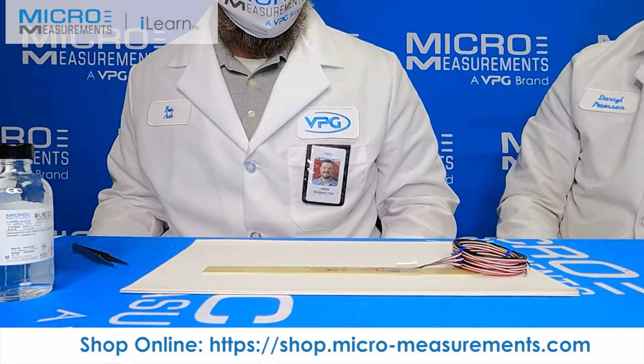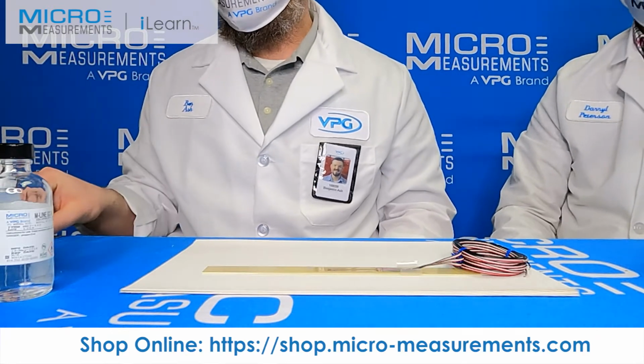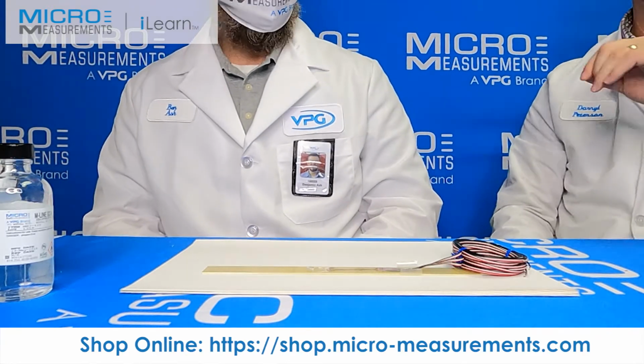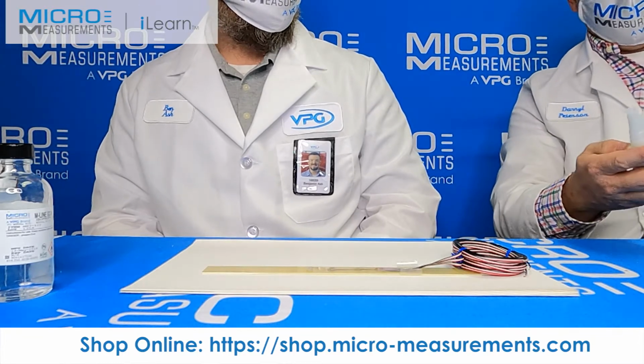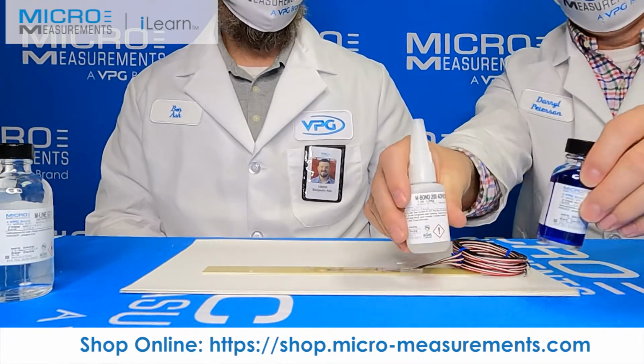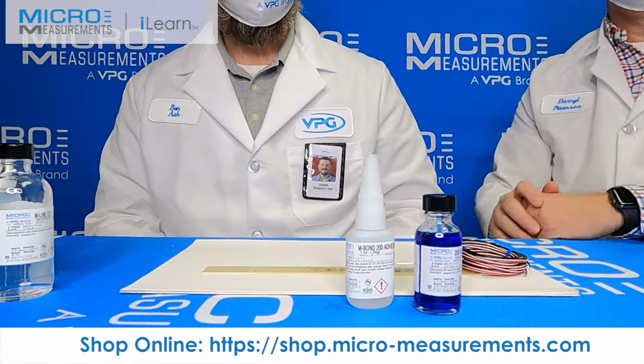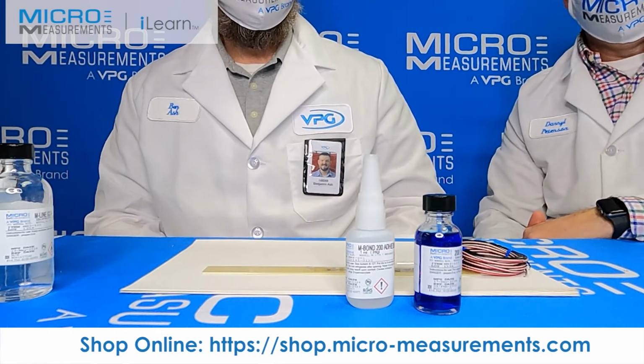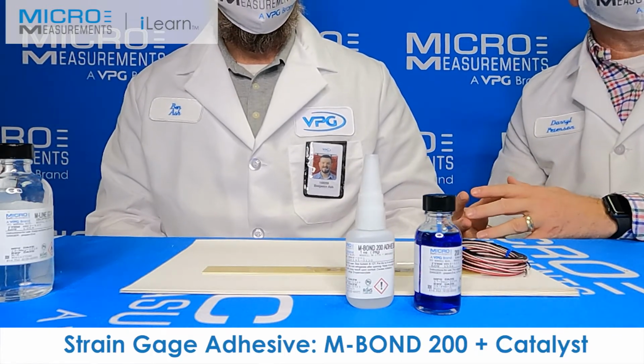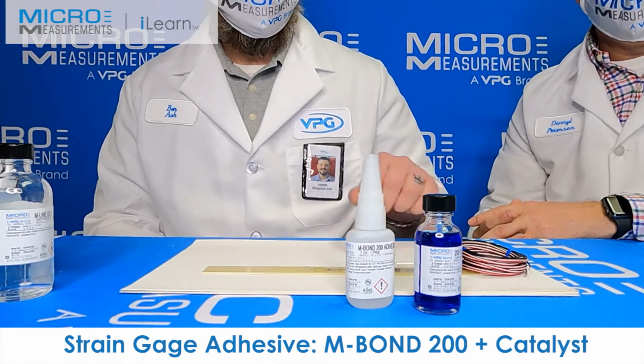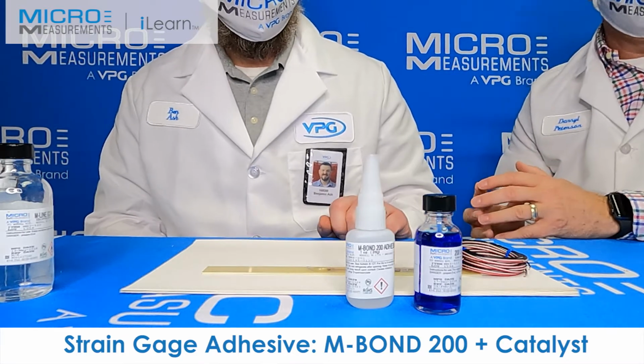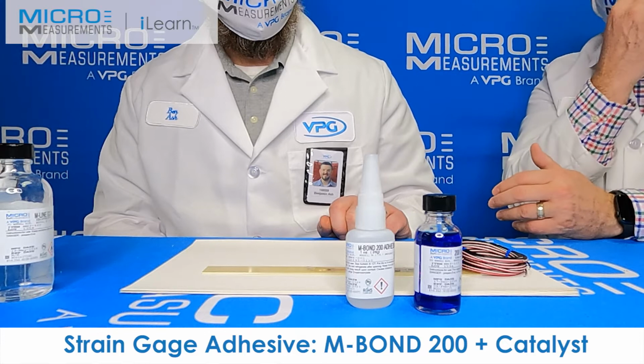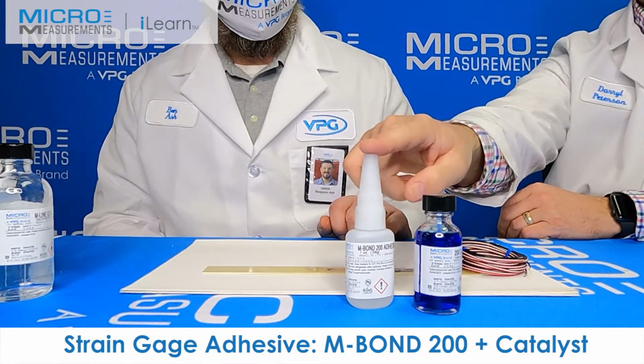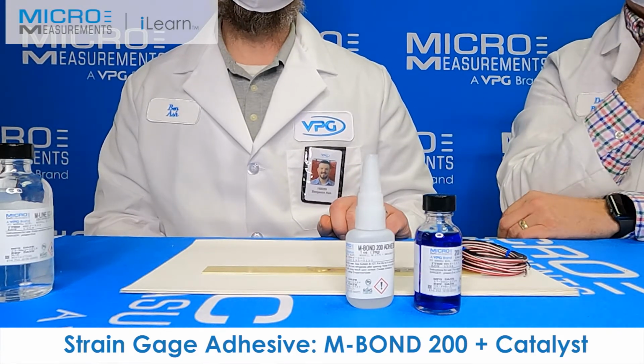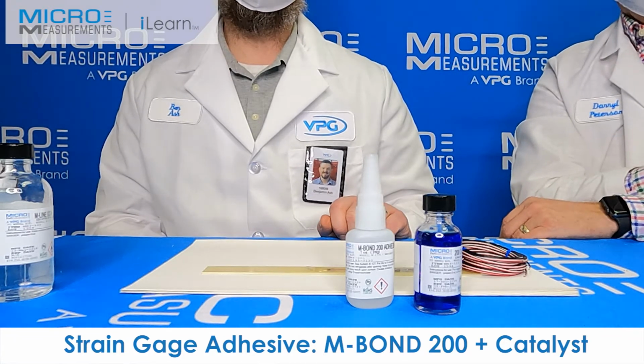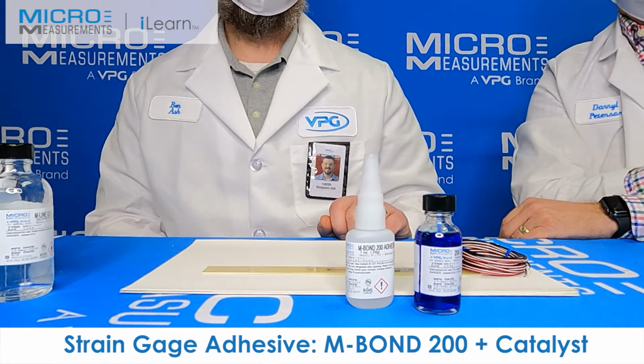All right. Now at this point, you're basically ready for the adhesive system. So we're going to use the MBond 200. This is our most common adhesive system that's used for experimental testing. MBond 200 is a cyanoacrylate, typically associated with room temperature or relatively moderate temperature testing. In general, you don't want to use this if you're getting up above about 150 degrees Fahrenheit or going below about minus 100 degrees Fahrenheit.